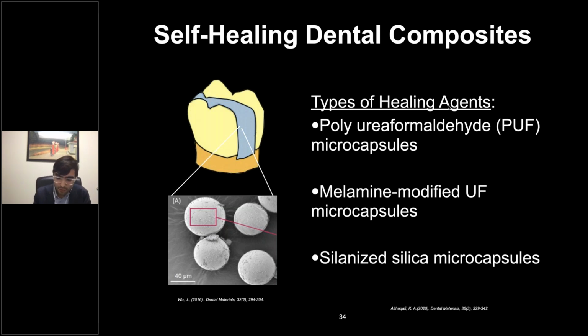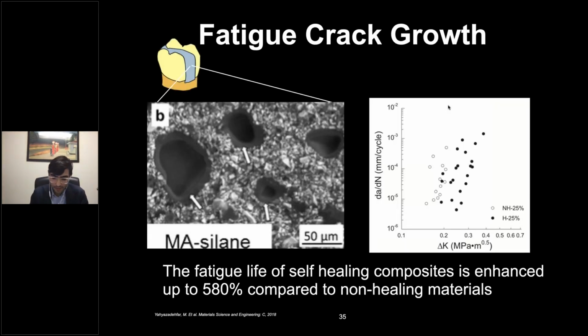Typical healing agents we're using in dentistry, PUFs, we're using melamine-modified and silanized silica microcapsules. We're putting these capsules inside the resin composites, and this study was done by Dr. Arola's lab in Washington. They show that if they embed these microcapsules and do the fatigue crack growth, da/dN over delta K, you need less amount of stress intensity to initiate, and the cracks grow at a slower rate, meaning the fatigue life of the material increases by 580%. So it's promising that these technologies are showing an increase in the fatigue life.